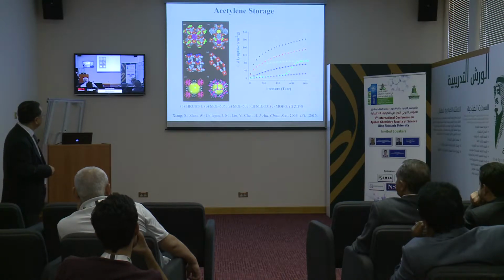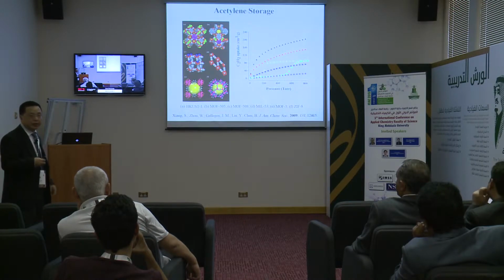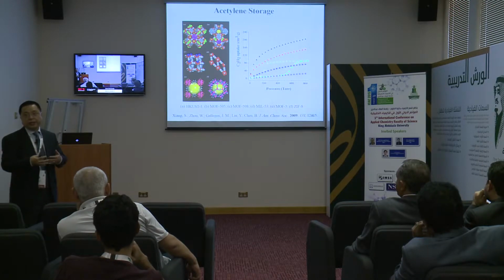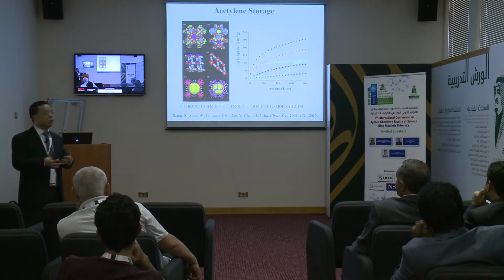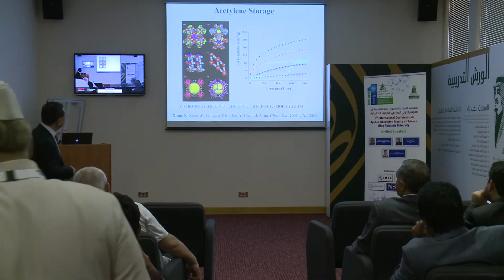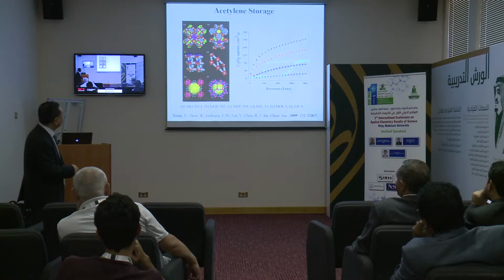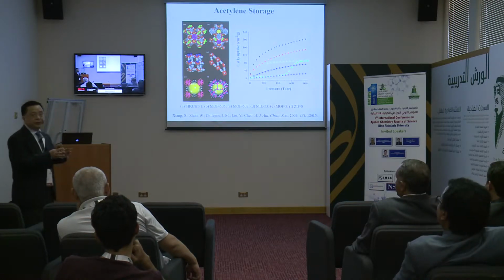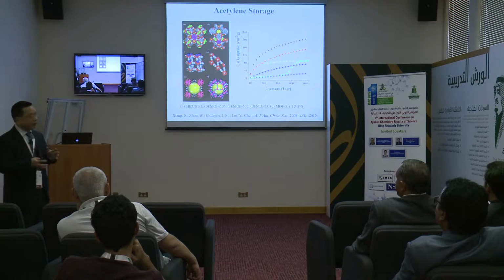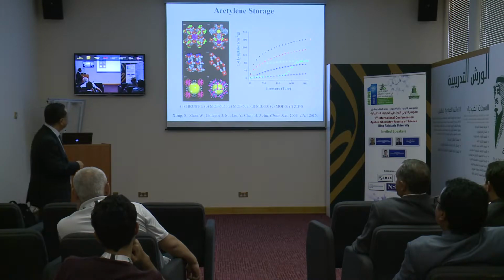Apparently, a highly porous one is not so efficient because this storage needs to be realized under very low pressure. Basically, here is 1 bar. So this space cannot be utilized for uptake, which is very low. But when we narrow down the pore, the uptake can be increased. And these two are specific because they have open metal sites. So the open metal sites enhance the interaction with the acetylene. So overall, this uptake is very high.